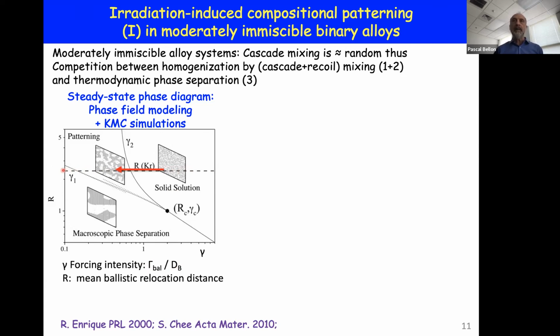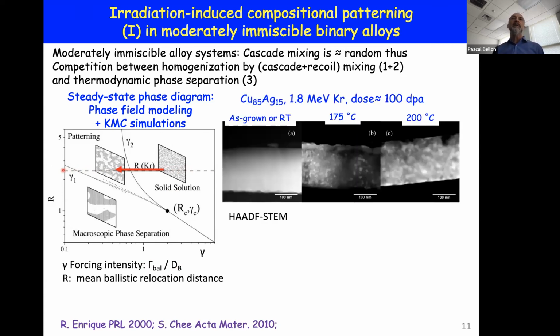cross this dashed line. And here's an example for copper silver, where in the as-grown state or irradiated at room temperature, cross sections in Z contrast and STEM mode show that we have a uniform alloy, so it's a solid solution. And then as we increase the irradiation temperature from room temperature to 175 to 200, we start observing the formation of precipitates in bright contrast here. And we monitored that after those, the size of these precipitates no longer changes with the dose.